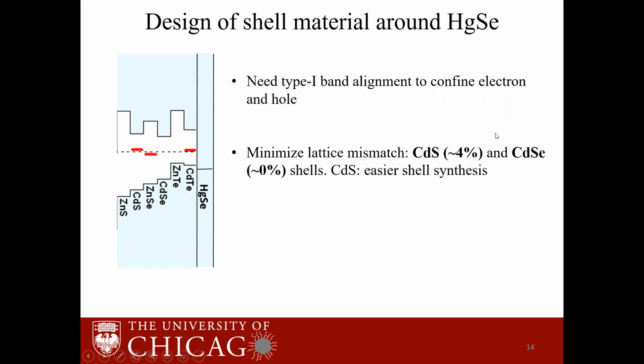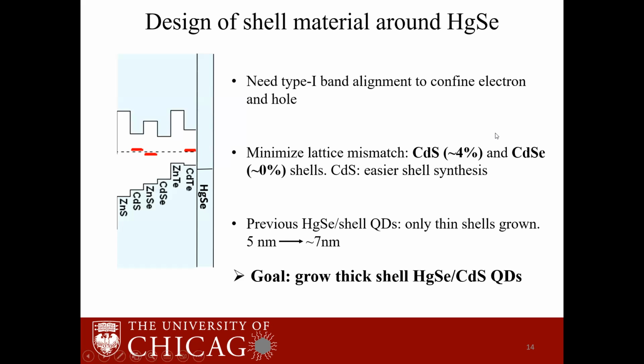And we have decided to grow a cadmium sulfide shell as the synthesis is easier than a cadmium selenide. Previous attempts to grow a shell on mercury selenide quantum dots have only succeeded in growing a very thin shell. So the goal of my project was to find ways to grow a thick cadmium sulfide shell around mercury selenide quantum dots. And as I mentioned before, growing a thick shell is synthetically a difficult task, especially on narrow bandgap